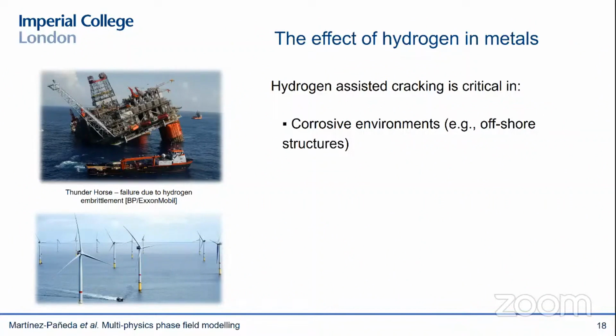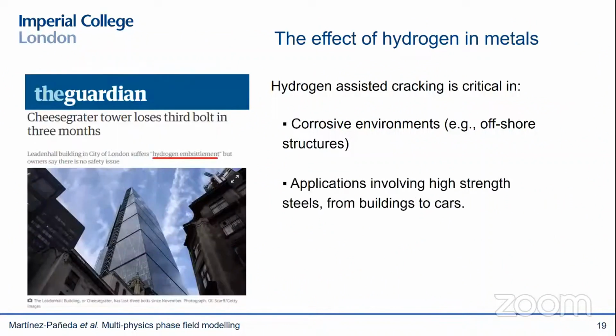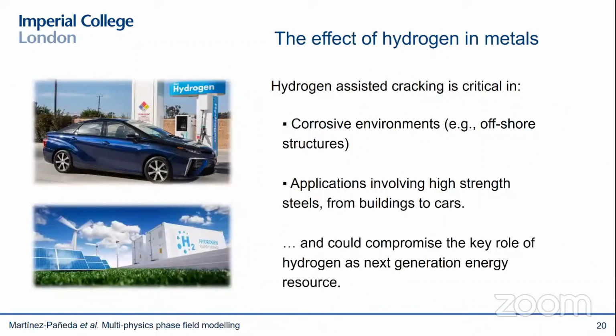But now we want to use these modern high-strength steels because they're very cost-effective. So we want to use them in our cars, in our buildings, in our bridges, in our railways. And this is triggering numerous hydrogen-assisted failure problems, you can see here, in otherwise very benign environments. This is a newspaper article from The Guardian, one of the main newspapers in the UK. And you can see that just the hydrogen coming from the humidity is enough to trigger hydrogen embrittlement problems in one of the most famous skyscrapers in London. And of course, this brings me back to my first motivation. If hydrogen can change by orders of magnitude the fracture toughness and crack growth rates in metals, how are we going to deploy this hydrogen energy infrastructure that we need to achieve net zero?